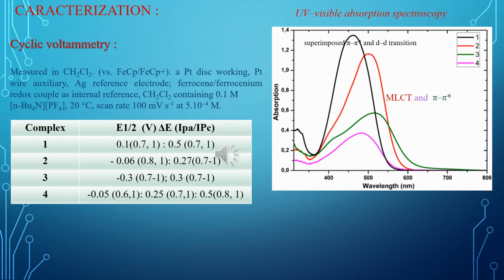By UV visible, the product 1 shows a wide and strong absorption band between 390 and 520 nanometer due to superposed pi-pi star and d-d transitions arising from the ferrocenyl, together with n-pi star and pi-pi star absorption bands of the azobenzene chromophore. The UV visible spectra for the alkynyl metal complexes 2, 3 show a broad absorption band from 380 to 550 nanometer that would correspond to the superposition of both MLCT and the pi-pi star absorption bands of the azobenzene chromophore.